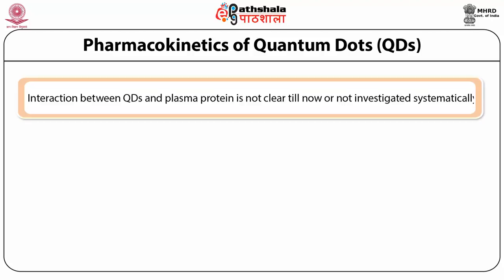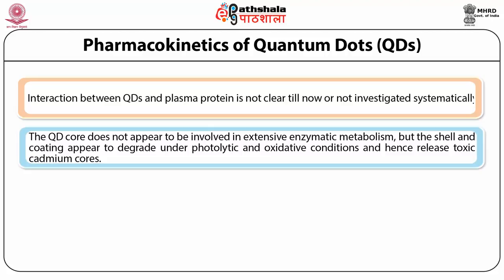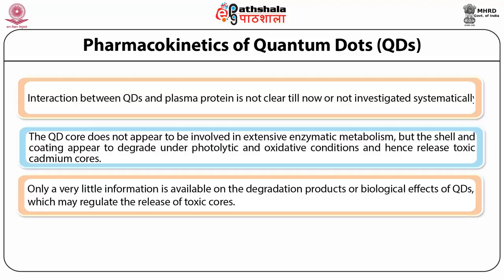The interaction between quantum dots and plasma proteins is not yet clear. The quantum dot core does not appear to be involved in extensive enzymatic metabolism, but the shell and coating appear to degrade under photolytic and oxidative conditions, releasing toxic cadmium cores — raising concerns about nanotoxicity. Only very little information is available on degradation products or biological effects of quantum dots, so no firm conclusions can be reached regarding their toxicity, efficacy, and safety without thorough systematic evaluation.